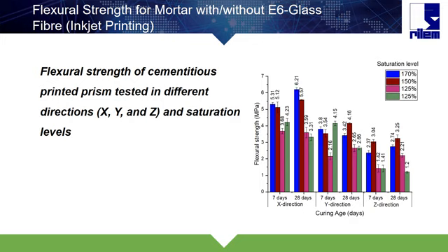When we have 28 days in the X direction, because as we know even the printed materials have orthotropic properties, not like normal concrete that has isotropic properties. Therefore, it's necessary to know that the printed material gives a very good result if we print it in the right direction and use it for the right purpose.